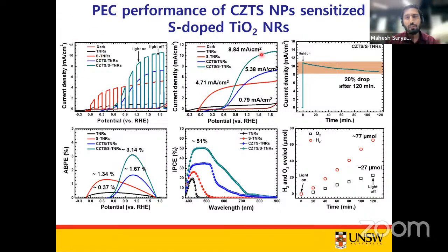These are the different measurement results after doping sulfur into TiO2 nanorods, then CZTS sensitization on TiO2 nanorods, and simultaneous CZTS incorporation into, or sensitization onto, sulfur doped TiO2 nanorods. As can be seen from these chopped and non-chopped LSVs, the CZTS sensitized sulfur doped TiO2 nanorods exhibited a significantly improved photocurrent density of about 8.84 milliampere per centimeter square, which is about 12 times higher than that of simple TiO2 nanorod arrays.